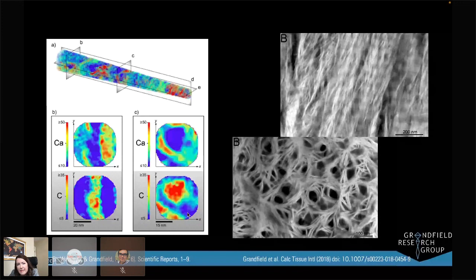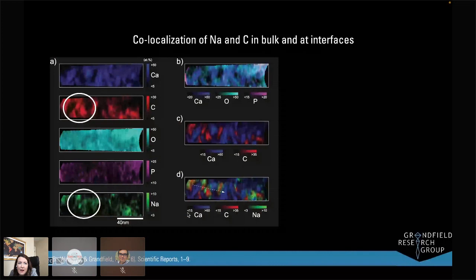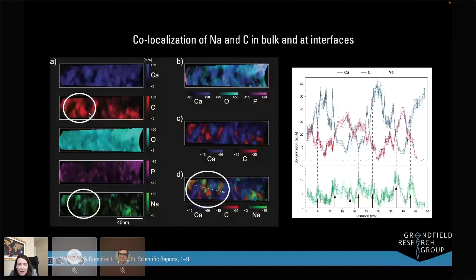We can explore this data further, and we see co-localization of trace elements such as sodium, an important element in some proteins, with the collagen fibrils. We also found that at interfaces between collagen and mineral, there's a peak in sodium, perhaps suggesting the role of proteins in templating the growth of hydroxyapatite along collagen.